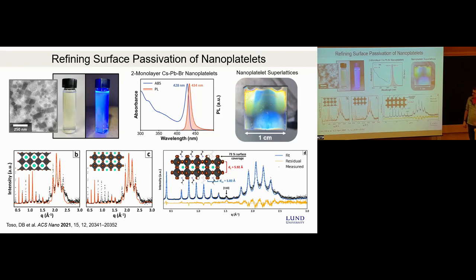Okay. So it's two octahedra with the cesium in between, and on the surface they're passivated, in our case, with allyl ammonium molecules. That does bring up an interesting question for what you showed in the previous slides, though: with the cubes, what's the size dispersity?